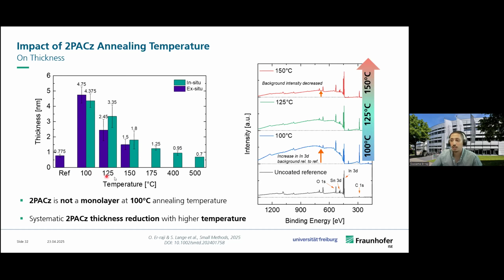But by increasing the annealing temperature, we saw that the fitted thickness really decreases towards a monolayer formation at around 150 degrees. Not only the SAM thickness was changed with the annealing series, but there were also changes in the work function and in the HOMO level. So from KPFM measurements, you can see that the shift of the work function was more than 0.2 electron volt at higher temperature.